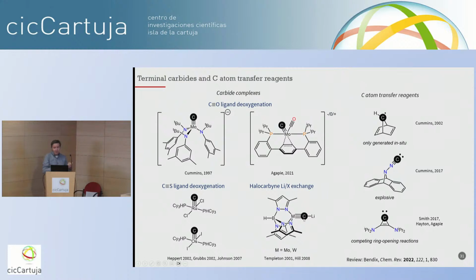One of the challenges of making a carbide is that there are not very good reagents for transferring a single carbon atom. So Kit Cummins' group developed this reagent, which is generated in situ. You can lose benzene and form a methylidyne that can be deprotonated. More recently, he made this compound. Again, you can see it's designed to lose N2 and anthracene and deliver a carbon atom. But this is an explosive compound, so that's sort of a reason not to use it. And then I showed earlier that this could transfer carbon to a nitride to make cyanide. But apparently, that's the only carbon atom transfer reaction this reagent does. We and also some other groups have looked at this, and there are other types of reactions that it does, particularly ring opening reactions that are not desirable.